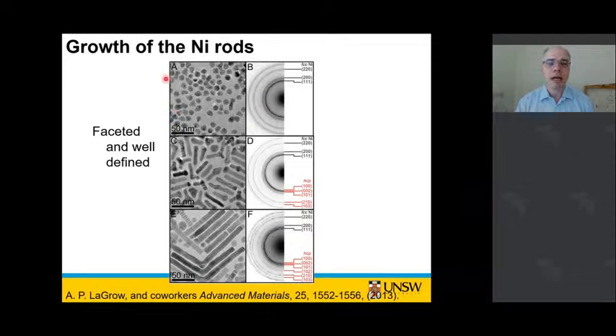So at the beginning of the reaction, when we look at the nuclei, we can look at the electron diffraction pattern, and we can see that we're forming predominantly or exclusively face-centered cubic nickel. So this is our cubic FCC nickel. And then as the branches start to grow off our nickel cores, we could look at the electron diffraction pattern and see how that changed. And we could see that we were starting to get some hexagonal close-packed structured nickel into the reaction as these particles were growing. And then as the arms grow longer and longer, we're actually ending up with more and more hexagonal close-packed nickel in our structures.